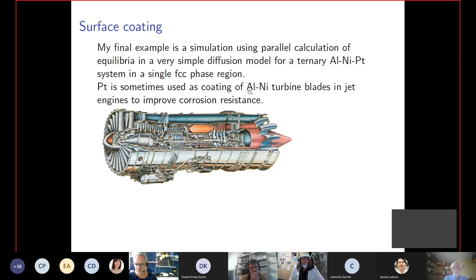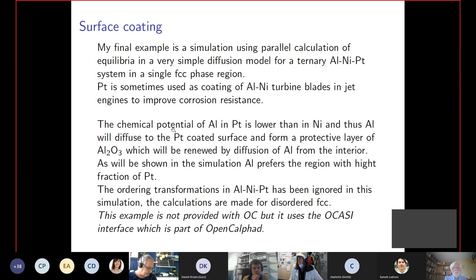But this aluminium nickel L1 two phase has very good properties both at high and low temperatures. But they also have corrosion problems, and they work in a very strange region down here. So, for example, to improve the corrosion resistance, you have sulfur and oxygen corroding the blades here. Sometimes platinum is used for coating of these turbine blades. And I try to simulate what is happening during this kind of coating. So aluminium oxide is always a good protection for corrosion. And this is not part of the OpenCalphad system, but there is a software interface to OpenCalphad where you can write a simulation program, and then you can try to see what is happening with time.